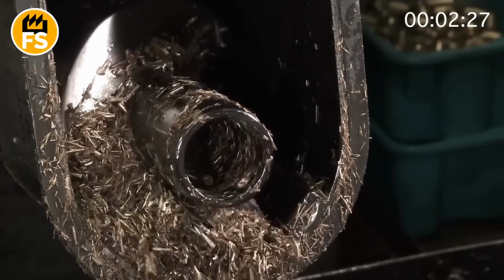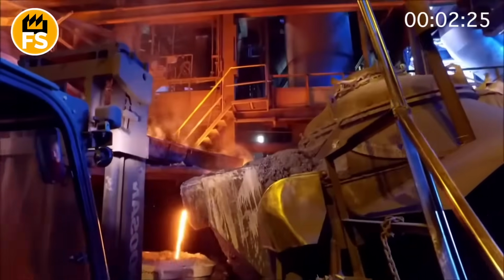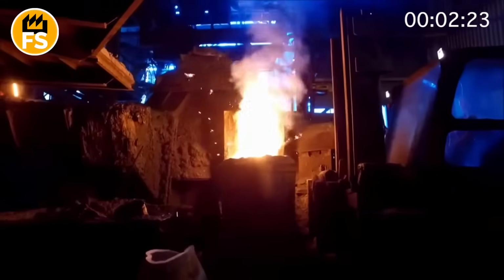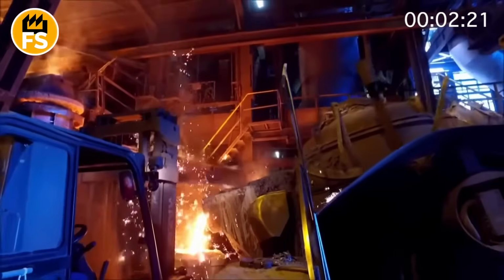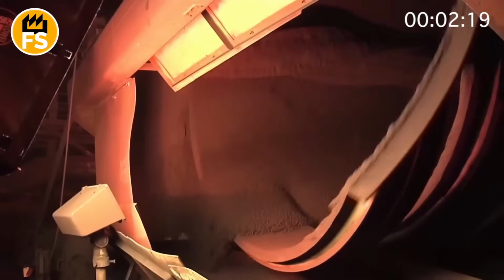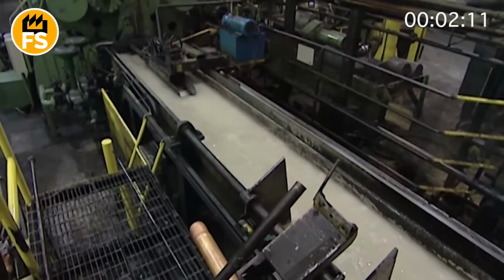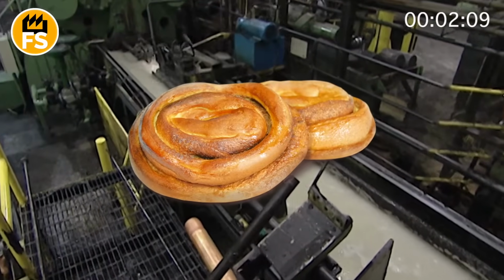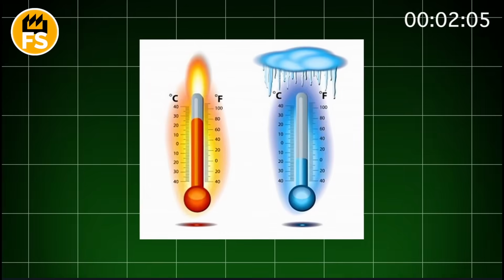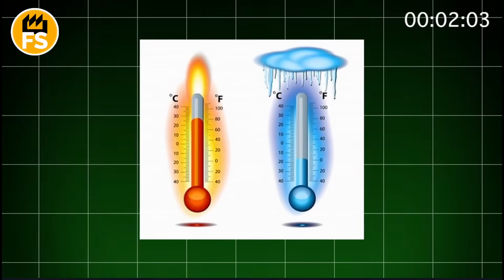It is turned from a flat strip into a cylinder, which is then welded along the seam or blown into a pipe shape. This process is very precise. The diameter and wall thickness are regulated with great accuracy so that the tubes can withstand pressure and don't burst. After forming, the copper tubes are still hot, almost like a freshly baked bun. To prevent them from deforming and to keep their perfect shape, they are cooled quickly.